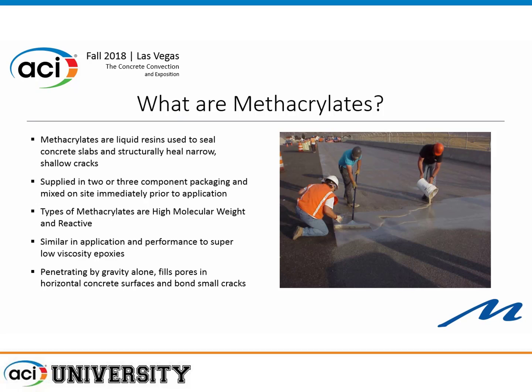Here's a photograph of installing methacrylates. You can see they're very low viscosity, similar to epoxies. The advantage of a methacrylate is that it can be used to seal and structurally heal some cracks. The newer formulations are typically done in a two-part application, although methacrylates chemically are three-part applications and they pre-mix two parts. If you mix the two parts together in the wrong order for the three parts, they can actually react and explode and become very dangerous. The newer ones are pre-mixed such that you can't really do that.